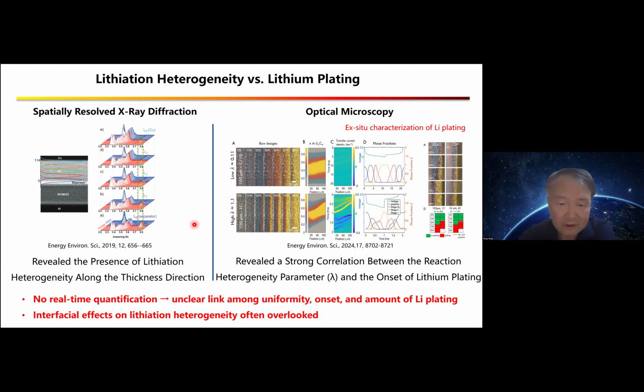People have used different techniques, such as spatially resolved X-ray diffraction, to reveal the presence of the lithiation process, and found heterogeneity along the thickness direction. Even for optical microscopy, you can see the color change of graphite corresponding to the lithiation stage, and there's a strong correlation between the reaction heterogeneity parameters and the onset of lithium plating.